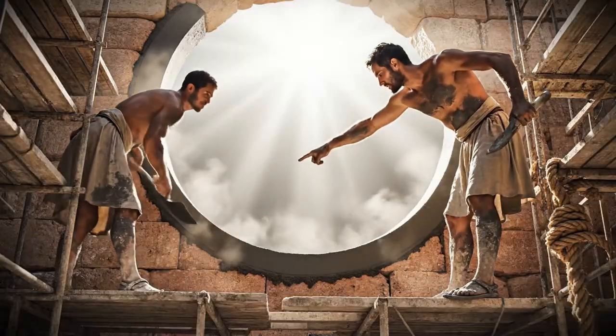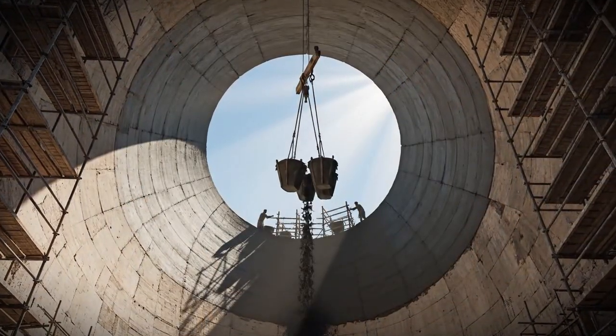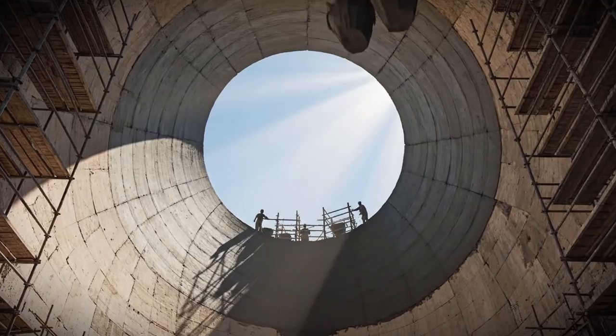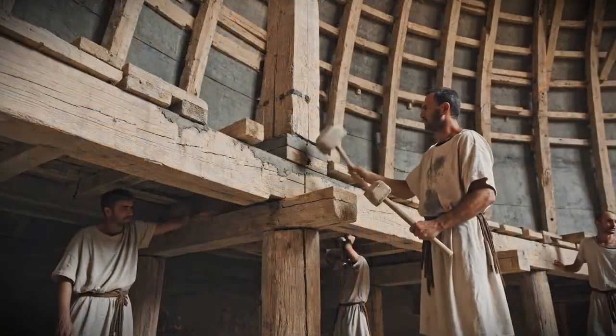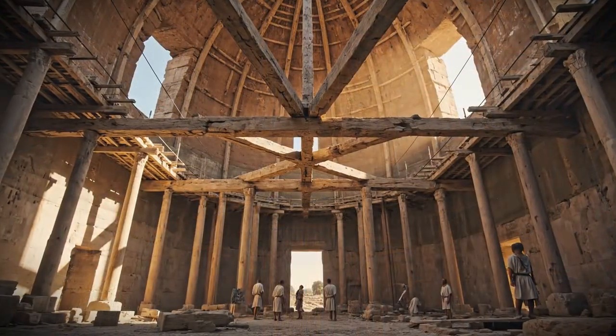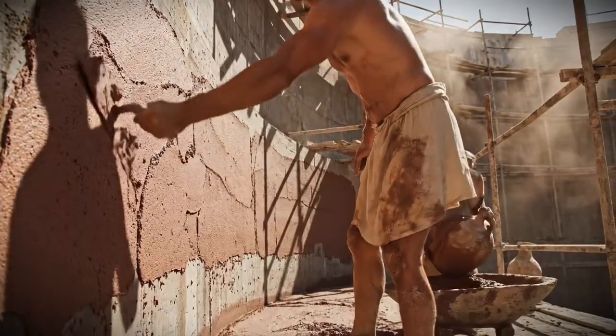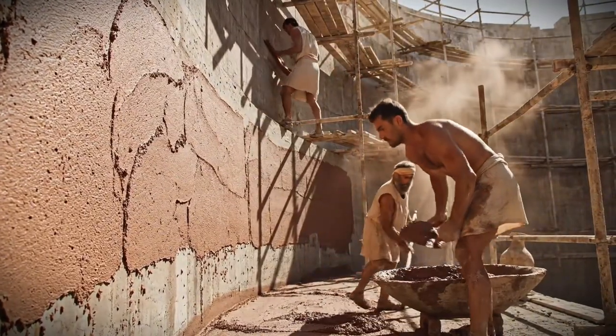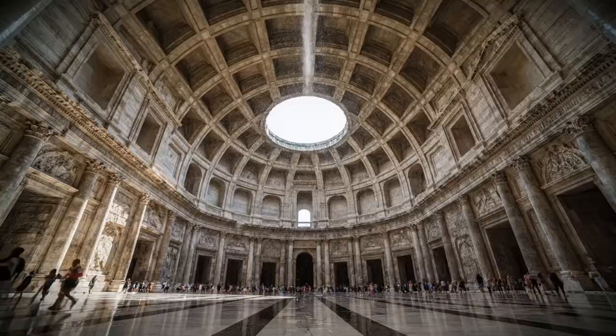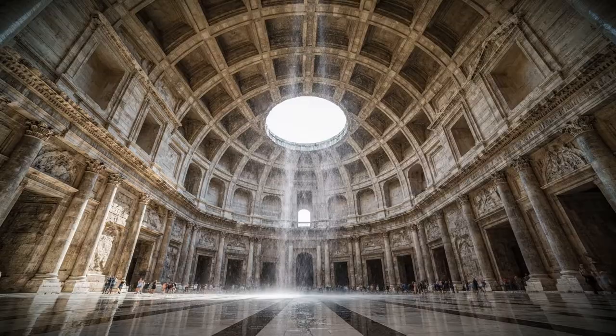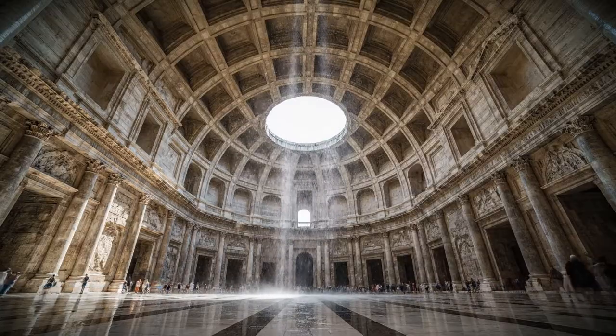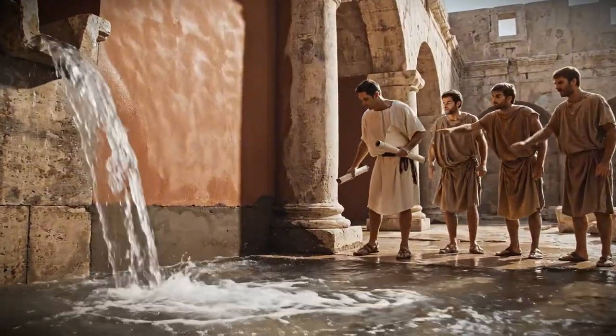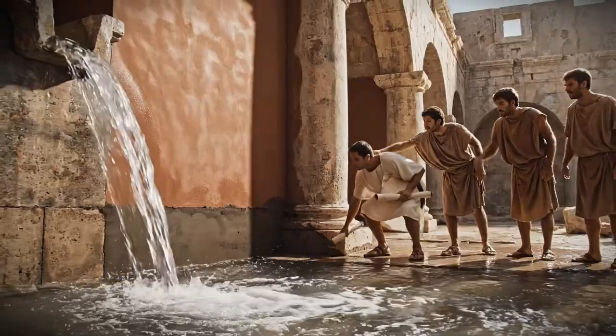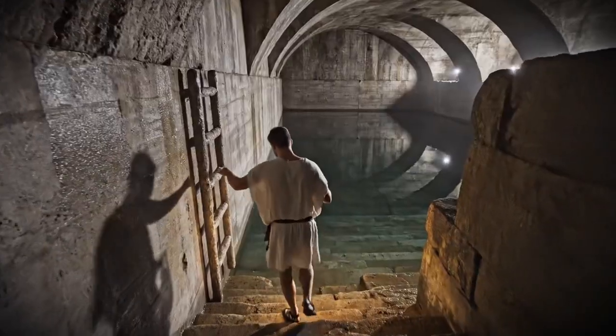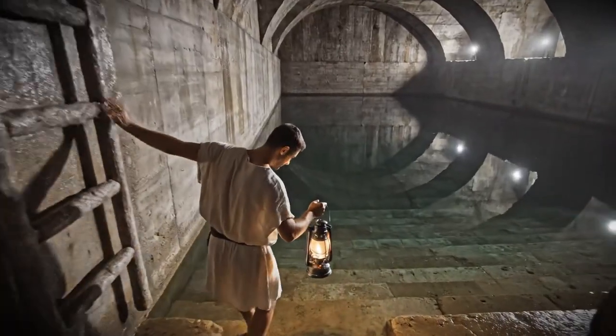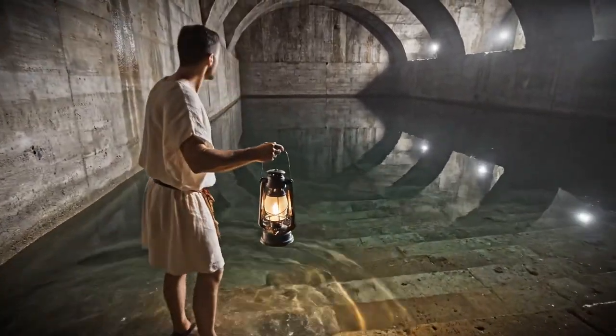The chemistry occurring within this submerged concrete was extraordinary. When seawater interacted with the lime and pozzolana mixture, it triggered the formation of aluminum tobermorite and philipsite crystals. These minerals grew within the concrete's pore spaces, filling tiny cracks and voids. Unlike modern concrete that becomes more porous and weaker over time as it's exposed to seawater, Roman marine concrete became denser and stronger. The process was slow, taking decades or even centuries, but it meant that the oldest structures were often the most durable. Modern analysis of concrete cores from the harbor at Caesarea, built around 25 BC, shows that the material is still chemically active today, nearly 2,000 years later.